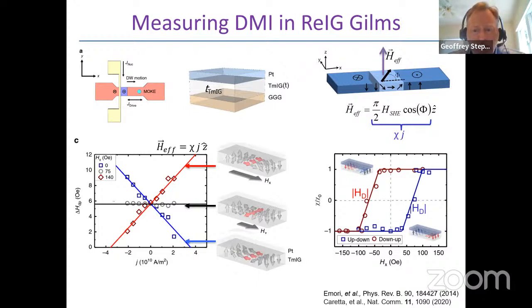In the publication shown at the bottom right, we have a protocol to quantify the DMI. Essentially, a Néel wall will be driven in a direction by spin orbit torque that depends on whether it is left-handed or right-handed. And if a domain wall is Bloch, then it won't be driven at all. So if one has a Néel domain wall pointing to the right, one can see how much current, in essence, it takes to drive it.